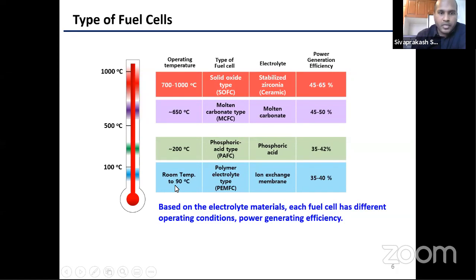The fourth one is the polymer electrolyte membrane, PEM, fuel cells, which work on an ion exchange membrane, for example the Nafion membrane, with an efficiency of about 35 to 40%.